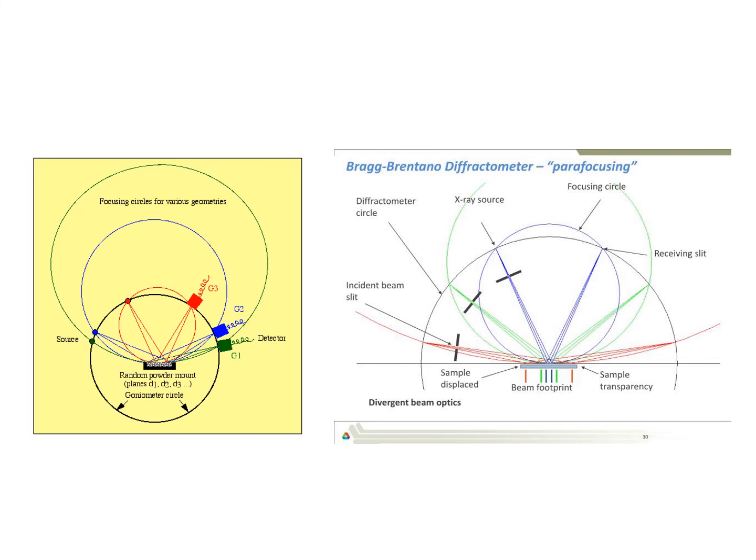But depending on what the diffraction angle is, the point at which we get this condition, what's called a focusing condition in a Bragg-Brentano focusing diffractometer, the area over which we have this focusing condition applied changes depending on what the diffraction angle is. More about that.